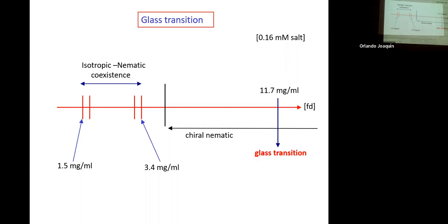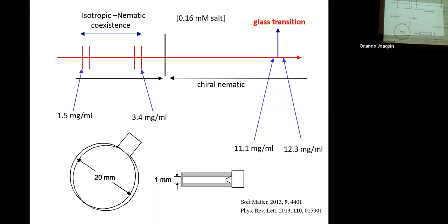Then here you find that resistance if the concentration is high enough—even though you have a low salt concentration, if you increase the concentration, the rods will nevertheless come closer together. That gives rise to a transition from isotropic to nematic. And if you go even further, you find here a glass transition. Now let me explain how we found it.